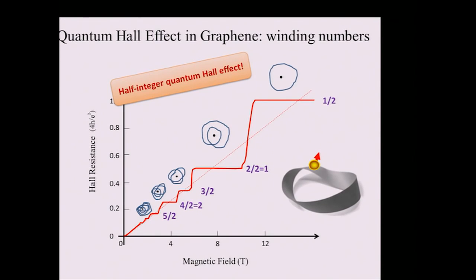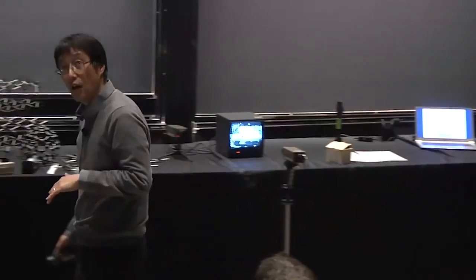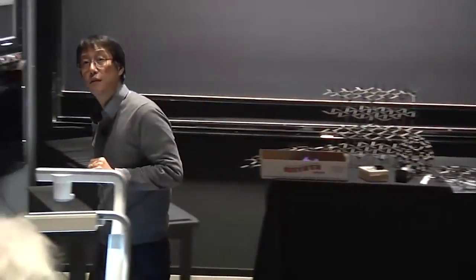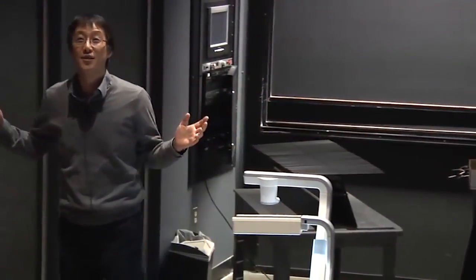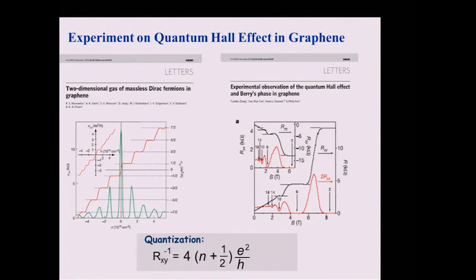And this can be tested experimentally because the step is appearing in your measurement. Indeed, only 1 year after the first discovery, both groups, and this time we didn't get scooped, luckily, started to see that indeed that's the case. When you measure the quantum Hall effect in graphene, it beautifully shows up and the step appears half integer rather than integer. Really showing that electron dynamics in graphene follow what relativistic quantum mechanics predicts.